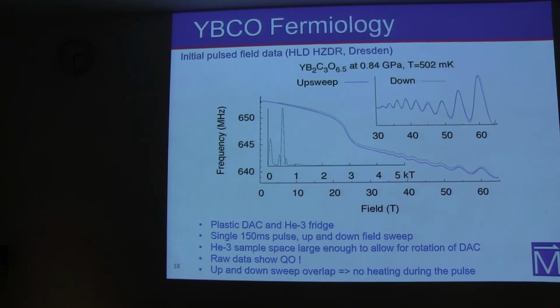And I know you are now going into a third axis, but can you guide us into what field or what part of the phase diagram you would be? Because presumably you will have some optimization of superconductivity. Are you on the right side of the dome or on the left side of the dome? So I'll show that later, but this is a rather small pressure, like 8 kilobar. So right now we're still on the underdoped side and still below the optimal part of the charge order. And how does that frequency compare with the one with doping? It's actually very close to the one with doping, and I'll show that later.